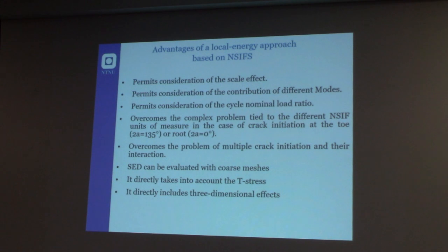But actually the advantage of the local strain energy density approach is that it automatically, now I will explain this approach a bit, is mainly based on 2 considerations. The first consideration is that if you have the notch stress intensity factor, you cannot compare notch opening angles with different sizes. So if you have a notch opening angle of 90 degrees and a notch opening angle of 135 degrees, you cannot directly compare the values because they have different units of measure.